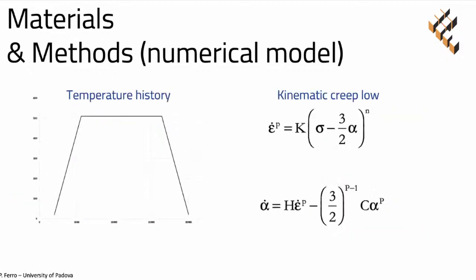After welding, we perform a numerical simulation of the post-welding heat treatment, the stress relief heat treatment. This is the recipe, the furnace recipe that we impose to the model as in the experiment. And we use this kinematic creep law in order to assess the stress relief during the heat treatment. The parameters of such a model are taken from literature and from the Sysweld database.